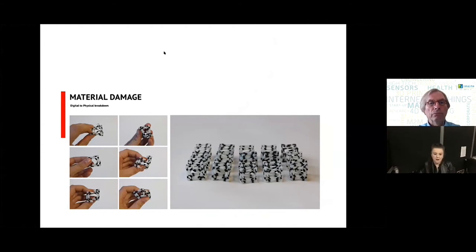But also there is a certain amount of damage seen at the vertex so we can design for that and increase the strut width and also the hinge radius to compensate for the weakness at the vertex but also ensuring that we haven't created an elasticity that is so high that the model is acting rather as an elastic lattice and not as an auxetic open cell foam.